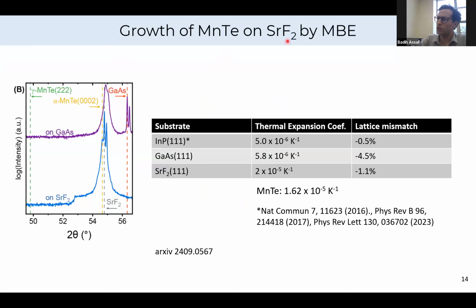Now, the reason why we choose strontium fluoride is because of the following. Notice that the thermal expansion coefficient of manganese telluride is quite high. It's about 1.6 × 10^-5 inverse Kelvin. That's at room temperature. And if you compare it to the thermal expansion coefficients of common III-V semiconductors, it turns out to be significantly higher.